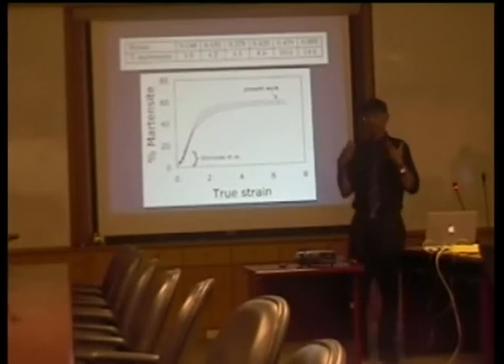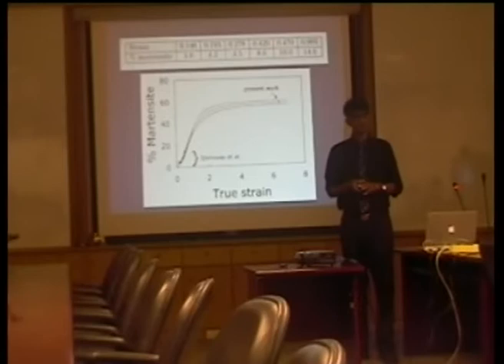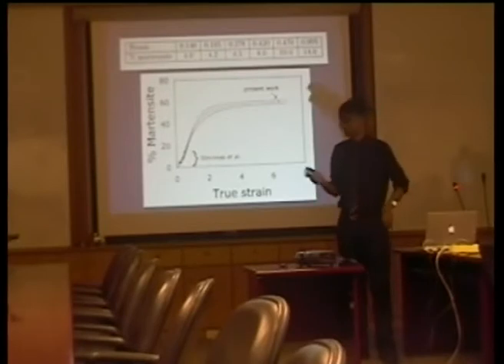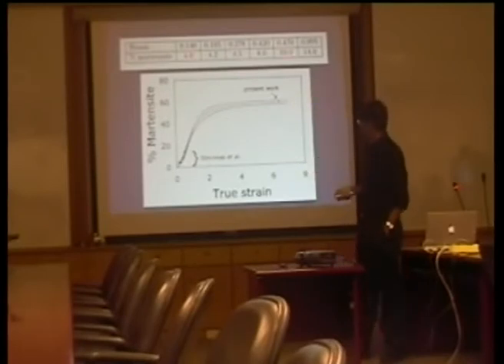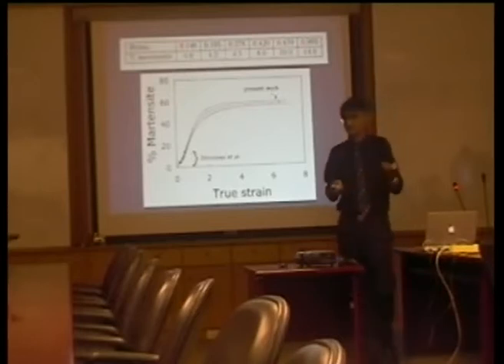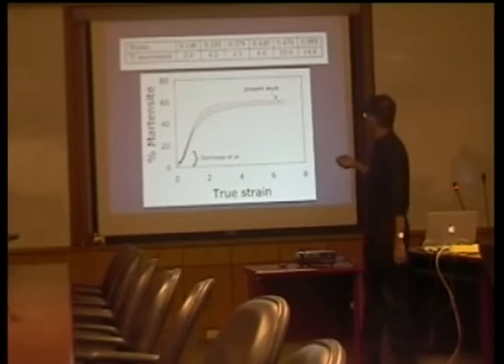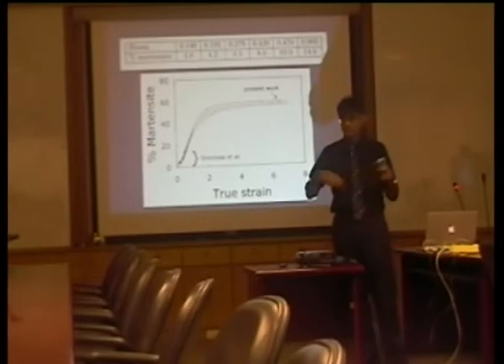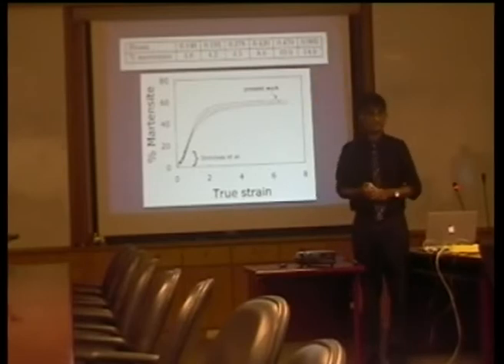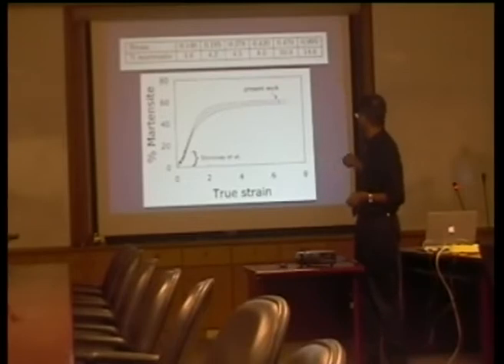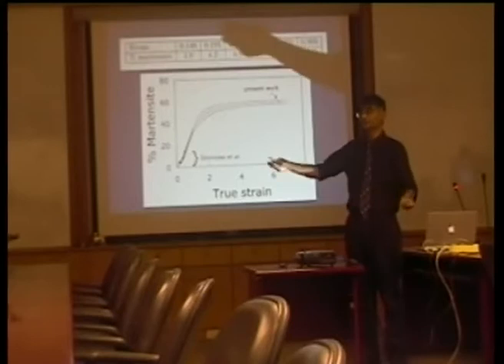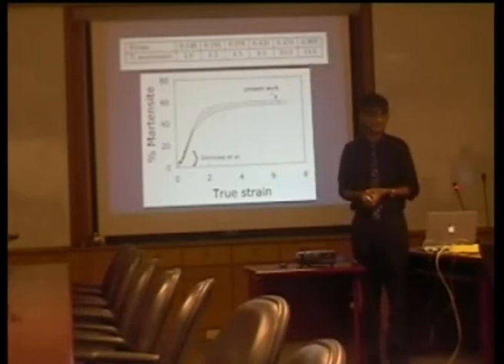Well, if we go back and look at the literature, many people have done experiments in which they deform 316L and look at the formation of martensite. So these are results from the published literature, where we are plotting the strain here, and these are fairly small strains, going up to 1. And this is the amount of martensite. And according to this, the amount of martensite should increase if I increase the strain. You can see that. And if I just look at these data, then I get a curve which looks like this. It should just continue increasing as I increase the amount of deformation.